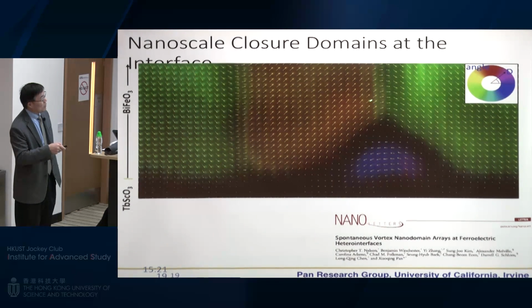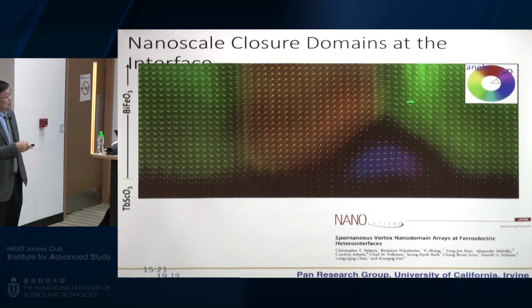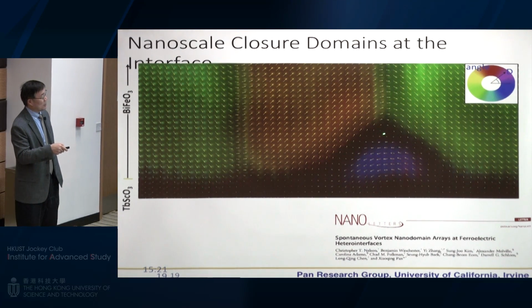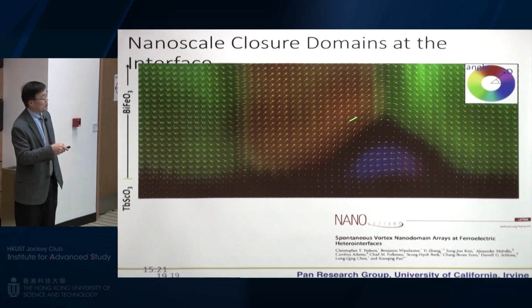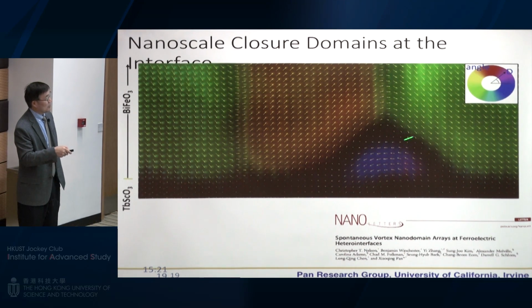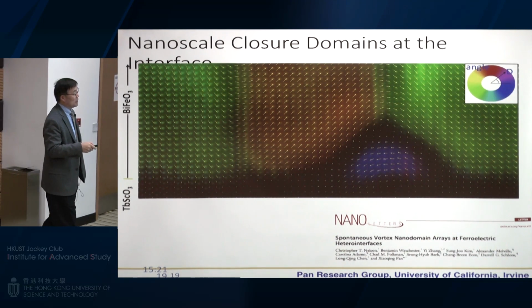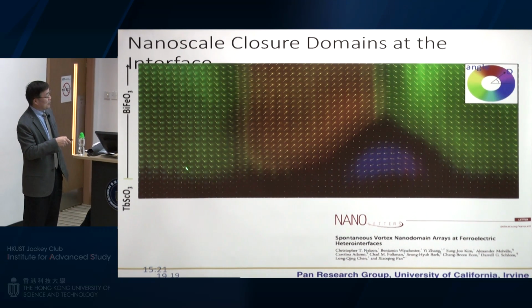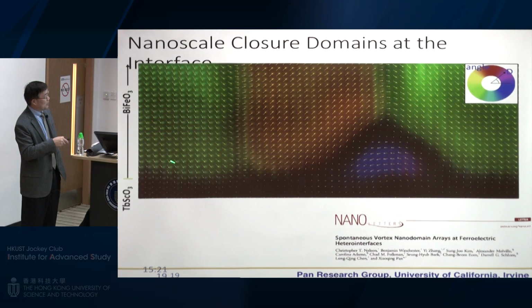And this next domain wall is also 109 degrees. If you compare this part and that part, they're just identical. But close to the termination point, the polarization no longer changes uniformly, and there is a rotation. We found ferroelectric vortices in the structure. These vortices occur periodically, at every other termination of the domain wall. This is due to the internal field created by the termination of this polarization.